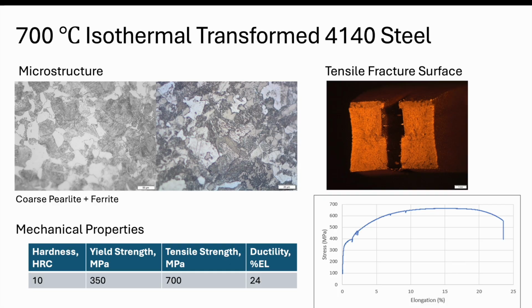So again, kind of thinking big picture, martensite has the highest hardness, the highest strengths, and the lowest ductility. Bainite's in the middle, so higher ductility, lower hardness, lower strength, and we go all the way up to pearlite, where we get our lowest strength and hardness, and then our ductility is the highest. So that kind of gives you the broad range of structures, and it all comes down to these different microstructures that we see. So the microstructure affects what these mechanical properties are, and by understanding that and by looking at it, we can predict what the mechanical properties are going to be.